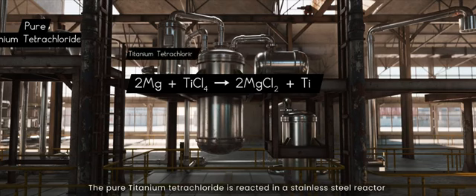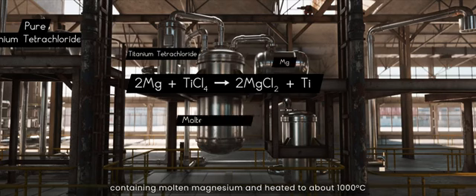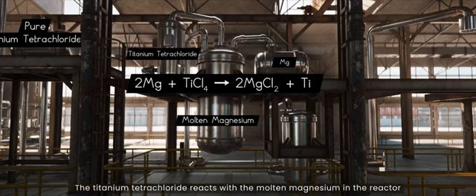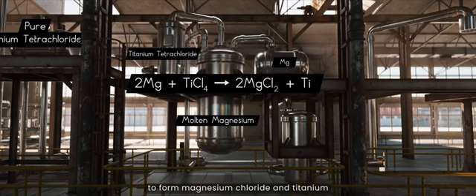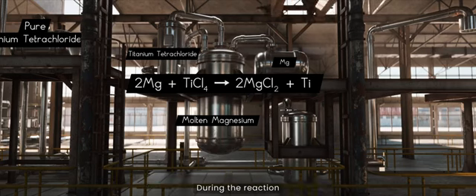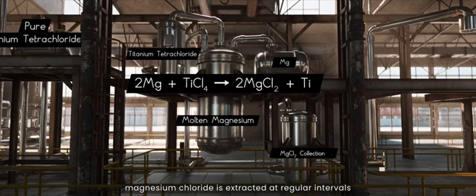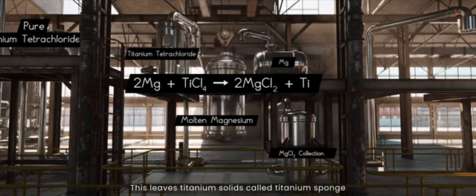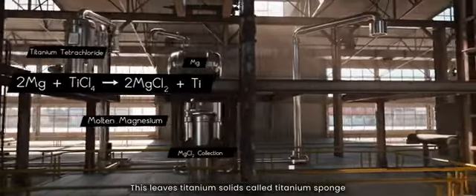The pure titanium tetrachloride is reacted in a stainless steel reactor containing molten magnesium and heated to about 1000 degrees centigrade. The titanium tetrachloride reacts with the molten magnesium in the reactor to form magnesium chloride and titanium. During the reaction, magnesium chloride is extracted at regular intervals. This leaves titanium solids called titanium sponge.